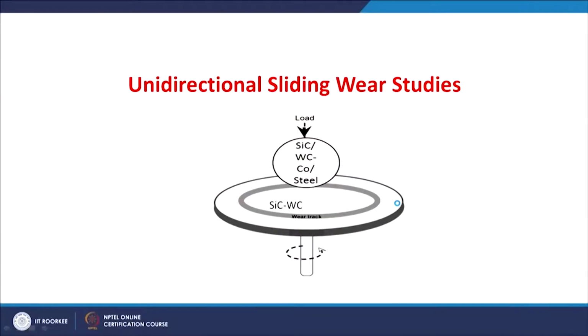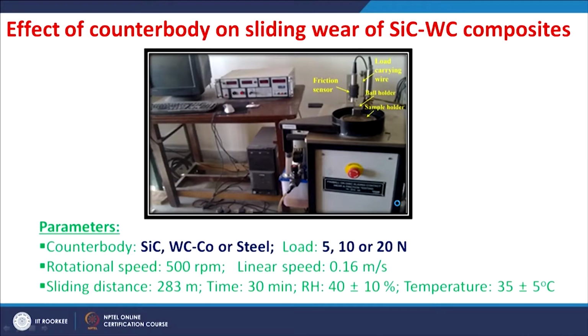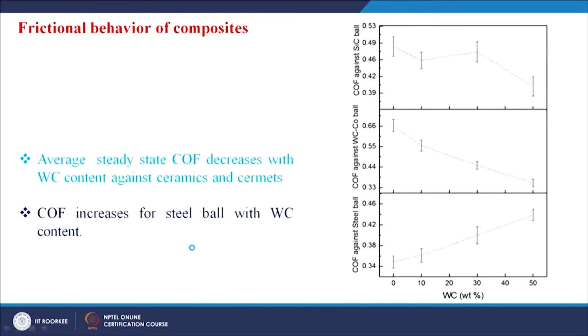So, let us go through the salient results obtained in unidirectional sliding wear studies. Mainly three different counter bodies were used: silicon carbide ceramic, tungsten carbide cobalt, which is called a cermet, and a steel. Three loads, separately 5, 10, and 20 Newton, were applied, with a combination of other parameters which were kept constant. For this, the ball on disc tribometer was used. So, the disc is the specimen, which is the silicon carbide tungsten carbide composite, whereas the ball is changed from silicon carbide to tungsten carbide cobalt or to steel, and the friction was measured and the wear was determined.